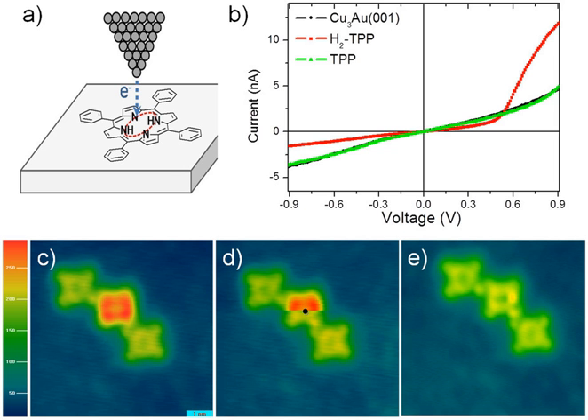When trying to measure electronic traits of molecules, artificial phenomena can occur that can be hard to distinguish from truly molecular behavior. Before they were discovered, these artifacts have mistakenly been published as being features pertaining to the molecules in question. Applying a voltage drop on the order of volts across a nanometer-sized junction results in a very strong electrical field. The field can cause metal atoms to migrate and eventually close the gap by a thin filament, which can be broken again when carrying a current. The two levels of conductance imitate molecular switching between a conductive and an isolating state of a molecule.